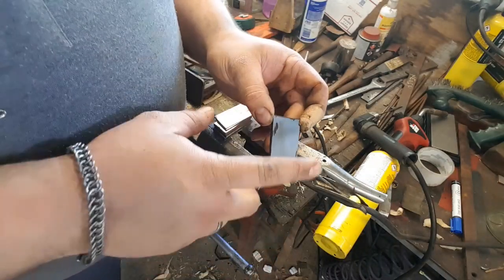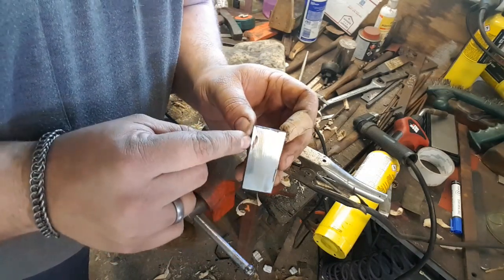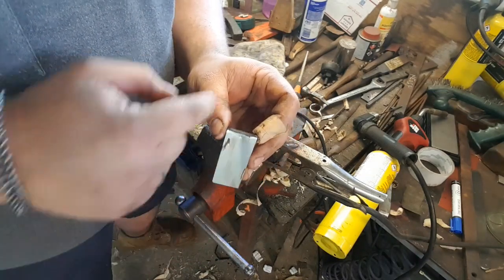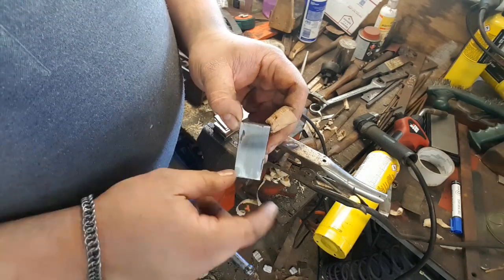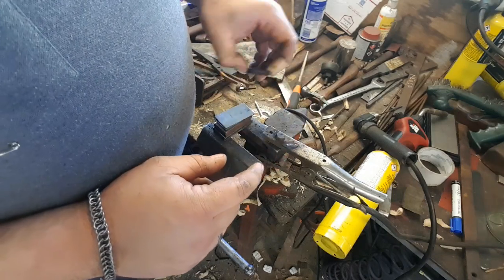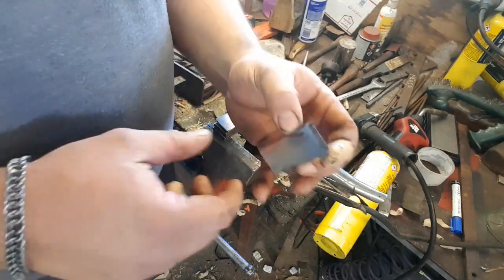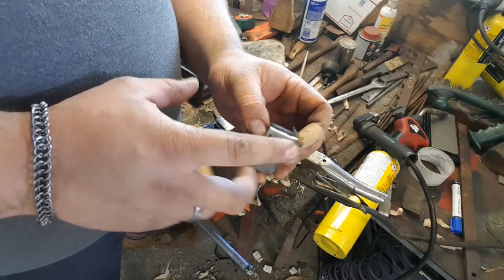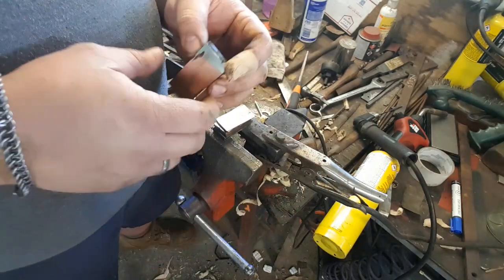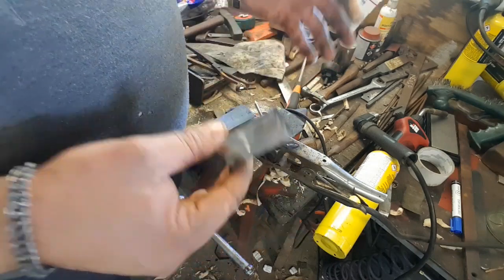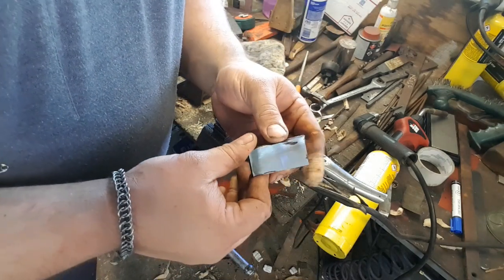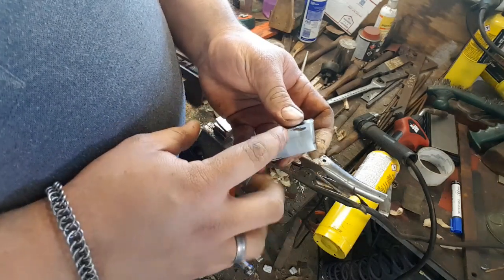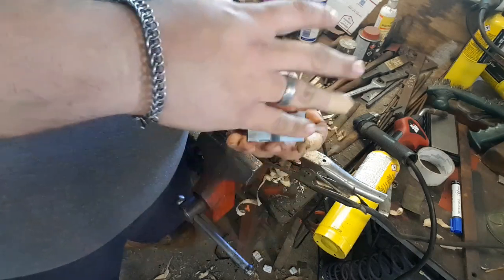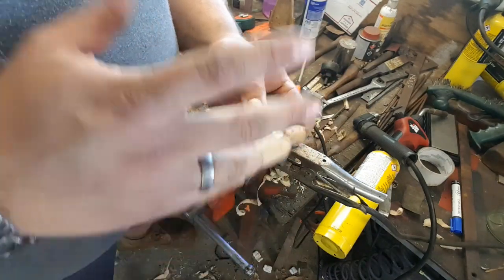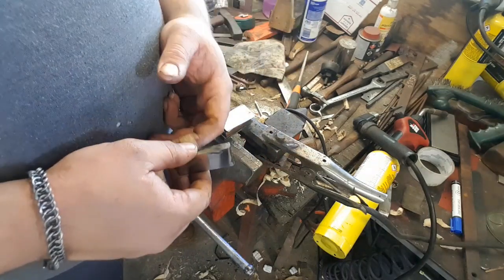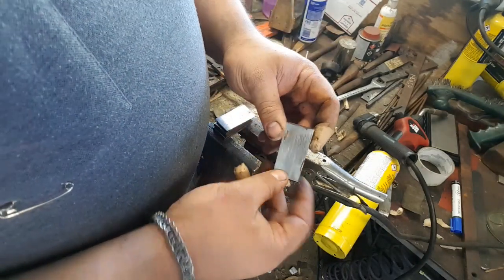Just something I noticed while I was stacking this billet, which I thought I'd cover. As you can see, this really nasty grinder mark here is where I obviously skipped off with the angle grinder when cutting this out of the leaf spring. If I was to put this on the side that's actually going to be welded, that would create a pocket of flux. And flux does not weld. Borax doesn't weld itself. It squirts out of the way after covering the steel and protecting it from oxidization. So that would immediately become an inclusion in my Damascus, which would mean that part will not have welded, which is a weak point in a knife, and if we're making a knife out of this, that could potentially cause a failure.